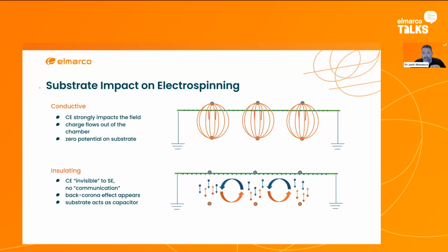So in the top case, you have a conductive substrate where you can make a good electric field between the collecting electrode and the spinning electrode, and you can see that it forms this sort of plume where the fibers come out. They expand a bit, but then they're trying to come back and collect on the wire electrode above. So that's the shape of the field whenever you're spinning. You can see it in the machine, and that's a good case. That's the case where you're probably spinning well. You're making a good coating, and the substrate's not blocking the communication, let's say, between the two.